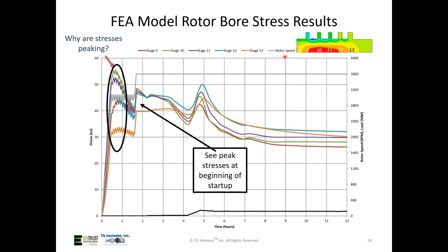So using this finite element analysis and the steam conditions, steam temperatures, pressures, and speed ramp rates, I can simulate the startup. And what you see is with this startup, if you follow the speed, it comes up to 3,000 RPM. It wobulates. For those that know the various startups, you probably know which OEM this is. But then it goes up from 3,000 RPM right up to 3,600 RPM and starts making power. Low load hold, and then picks up load eventually. So my question is why are stresses peaking so early on?